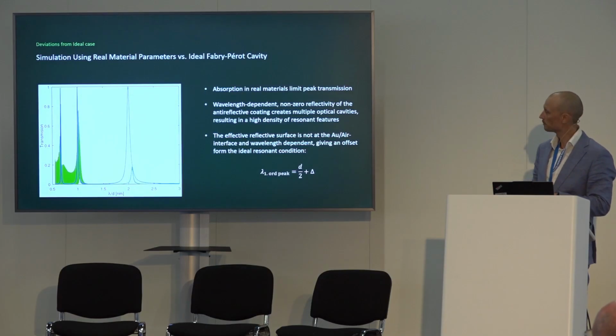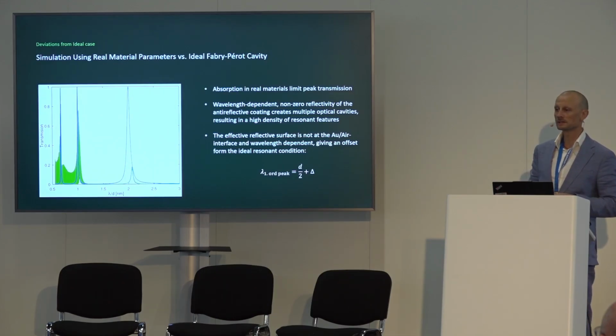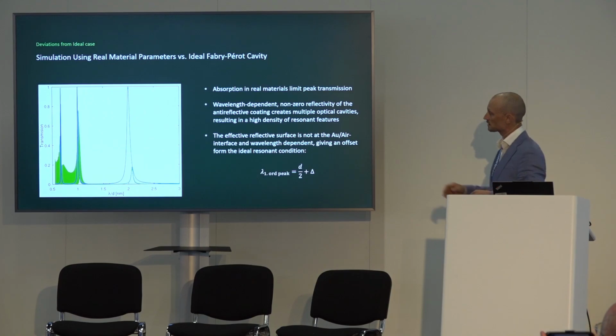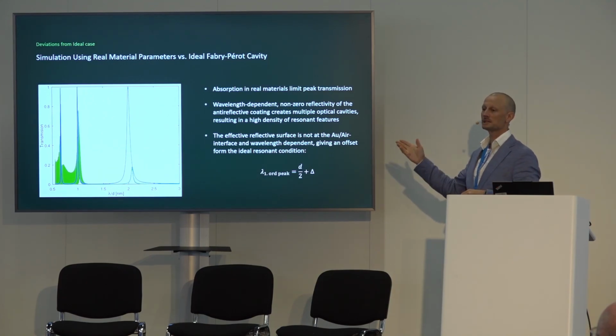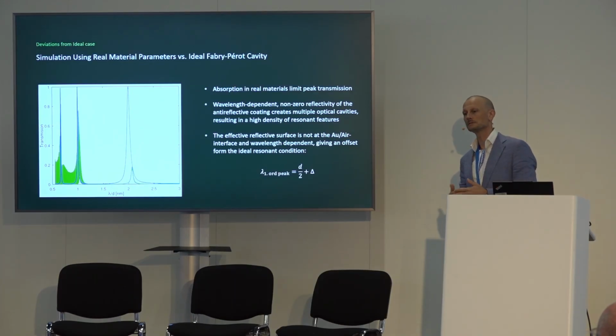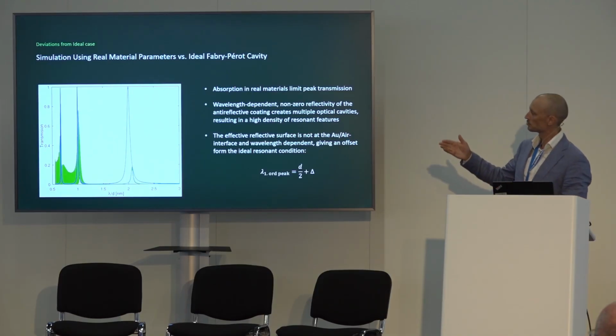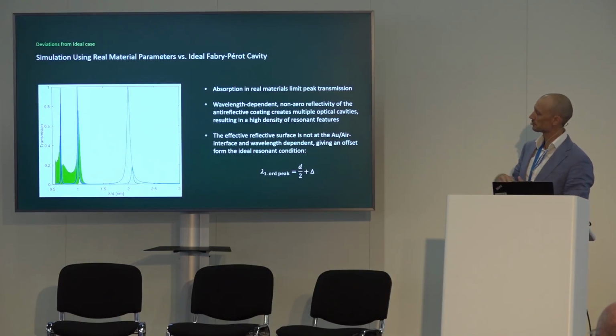Now, if we compare that to the theoretical plots, we see that there are a couple of other differences too. For example, the transmission is quite bad, in this case only 20% of the theory, and that's because we've used metal as our mirrors, and metal is a lossy material. You can also notice that the position of the peak is slightly shifted, and that's because the effective reflective surface is not located exactly at the gold-air interface.